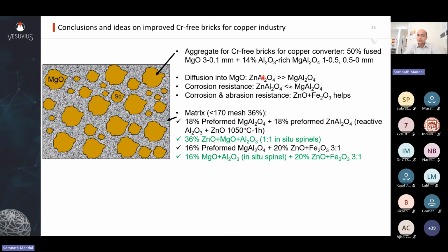Now, as we know, zinc aluminate has better diffusion into magnesia, so zinc aluminate should be used, and it gives you corrosion resistance, and zinc and iron doping helps. So your matrix, which is the remaining 36%, what would that be? Preferably 18% preformed spinel and 18% preformed zinc aluminate, and I have published a paper on this. There's a very easy way to manufacture it at 1050 degrees Celsius. You can make preformed zinc aluminate powder that can be used directly in the refractory.